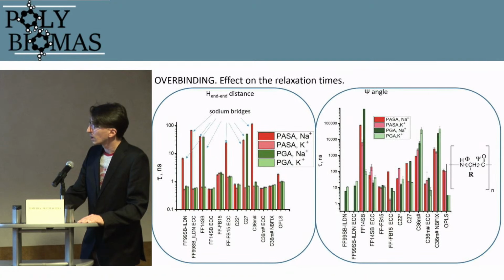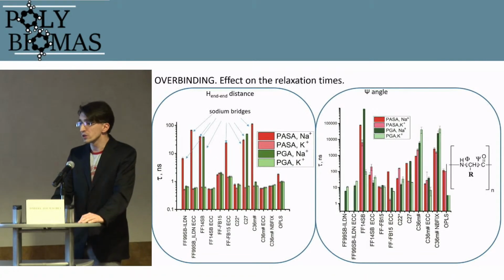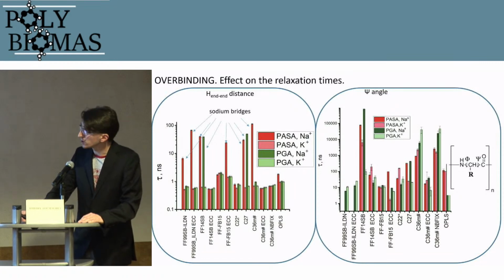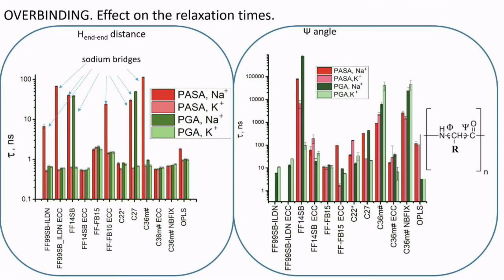So this is about structure, and also it is important to know that these artificial sodium bridges affect dynamic properties of the system. Here we can see the first graph shows the distance between the ends of the chain, and its relaxation time. And we can see that sodium bridges lead to an increase of relaxation time, sometimes even by several orders of magnitude, while in systems without sodium bridges, relaxation time is more or less the same.